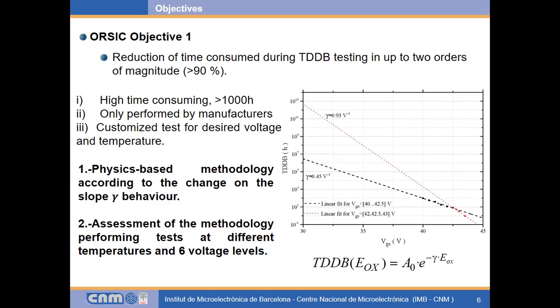And we would like to assess this methodology at different temperatures. Then the final user should be capable to perform this test in around 100 hours and to have an estimated lifetime for their application temperature and voltage.